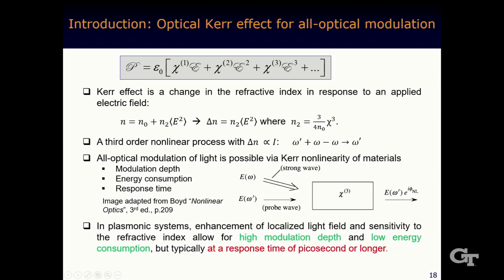If two beams are involved, like this one, a strong beam and then a weak beam, then apparently the strong beam will change the refractive index of this medium, which can be felt by a weak beam, the so-called probe beam. So this gives rise to the so-called all-optical modulation, because the behavior of this probe wave will be modulated by this strong wave. Metals have pretty large Chi3 response, therefore plasmonic structures making use of metals can give rise to pretty good modulation depths along with relatively low energy consumption. But on the other hand, metals also have pretty large thermal loading. That means the recovery of the property back to the unexcited state can take a very long time, picoseconds or even longer.